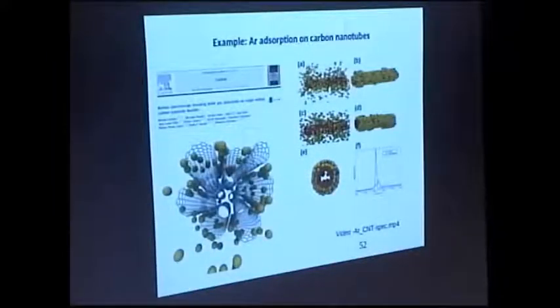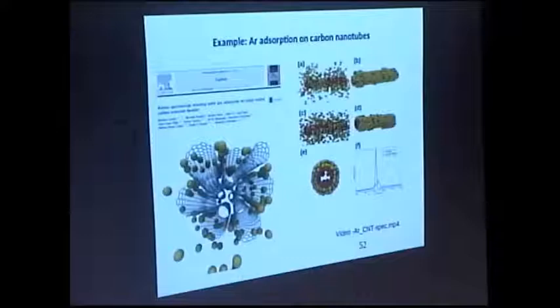Here is another example. In this case, we don't have many reactions, right? We have something that's dominated by van der Waals interactions. That was the adsorption of argon atoms on small single-layer nanotubes that was found experimentally by these guys who collaborate with Maurício Terrones, and I did simulations using ReaxFF to show what the configurations are that you can find here. I can show you, just one second. Let's see.